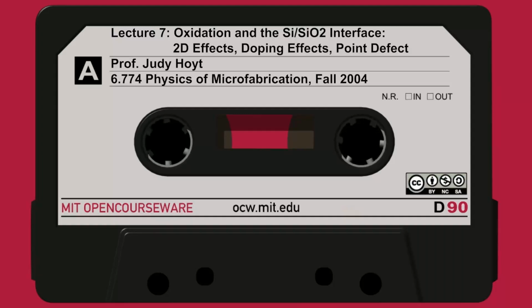In fact, if we go on to slide 27, this is some data from the literature on the stacking fault length here on the y-axis as a function of oxidation time. At different temperatures here, 1200 is up at the top. This is 1050. And so you can see the stacking fault length increases with time of oxidation. And the growth rate is faster for higher temperatures. So if we go here, 1050, 1100, 1150, the growth rate is faster.